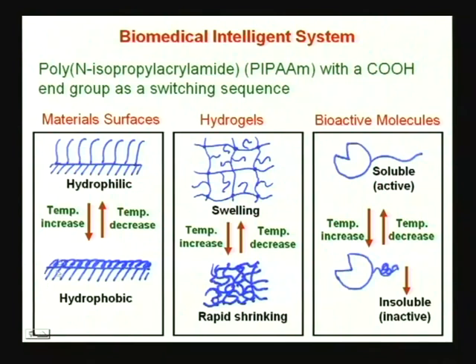Now, here you see one surface represented by this portion. This surface is modified, or coated, with such N-isopropyl acrylamide polymer. Okay. Now, two cases are shown over here. When the system temperature is increased, you see there is shrinkage of the molecules which are attached to the surface. When the temperature is decreased, this shrinkage is reversed and the molecules expand and show swelling